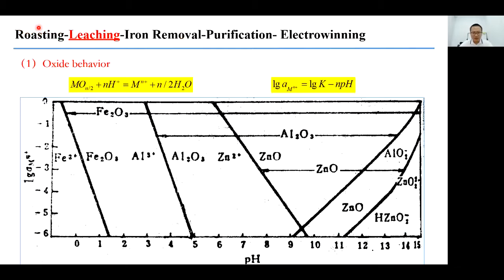Okay, so this is the roasting part. We got to the conclusion. The zinc sulfide will convert mainly to zinc oxide, and some of it will stay as zinc sulfide. The other impurities like lead are converted into lead sulfate. Iron will make zinc ferrite, which is a headache in the following part. And the copper will stay as copper oxide, which can be easily processed.